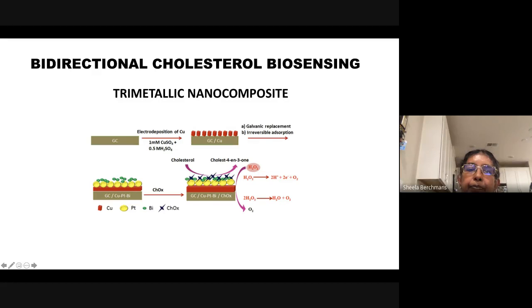Also, we have attached cholesterol oxidase enzyme to glassy carbon electrodes using trimetallic nanocomposite. We have used copper, platinum, bismuth nanocomposite for the immobilization of cholesterol oxidase. We have shown that cholesterol on oxidation gives cholestenone plus H2O2. The obtained H2O2 can either be oxidized or reduced. So we are able to do the oxidation of hydrogen peroxide as well as reduction of hydrogen peroxide. So we can sense the cholesterol either anodically or cathodically. That we have achieved in this work.